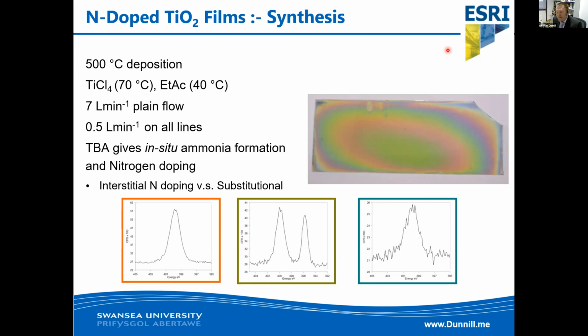XPS here is a fantastic technique, as we have heard about today from Mark. But XPS here is actually really useful because we can tell the difference between interstitial and substitutional. It is, however, very, very difficult to make samples that have only one form, whether it be interstitial or substitutional. The green sample in the middle is what normally occurs where you have both.